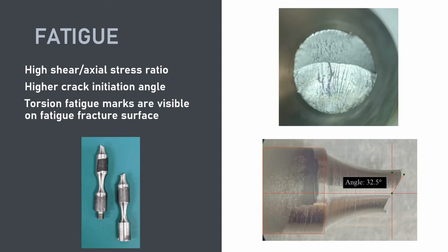Comparing now to a higher shear specimen, it is still on the surface right here, the point where the initiation occurred, but we obtained a higher angle of initiation, and we also can see marks which are associated with torsion fatigue.